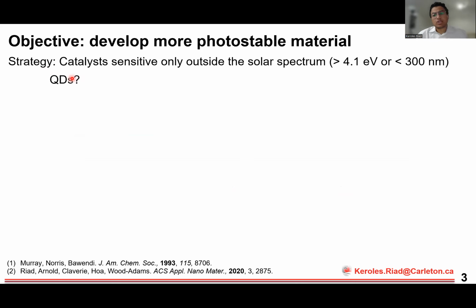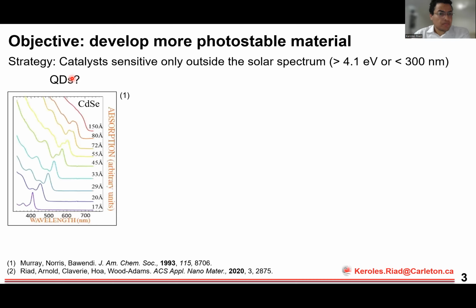And quantum dots are a special kind of semiconducting nanoparticles whose band gap energy is a function of their size once the crystal size is below a certain threshold called the Bohr diameter. So in this graph here is cadmium selenide, where the crystal size goes from 150 angstrom all the way down to 17 angstrom. And you see as the crystal size decreases, the absorption wavelengths plotted on the x-axis shift to the left to lower values, and that means a higher bandgap energy. And so in essence, as the crystal size decreases in quantum dots, the bandgap energy increases.